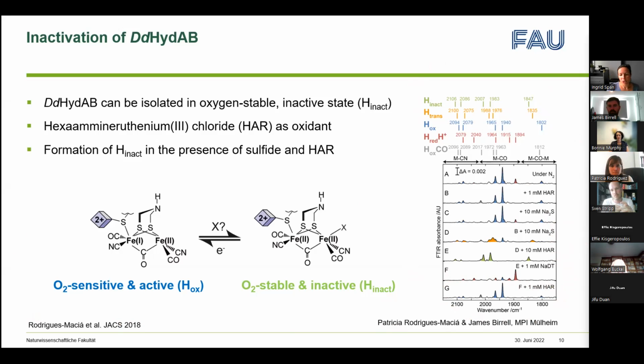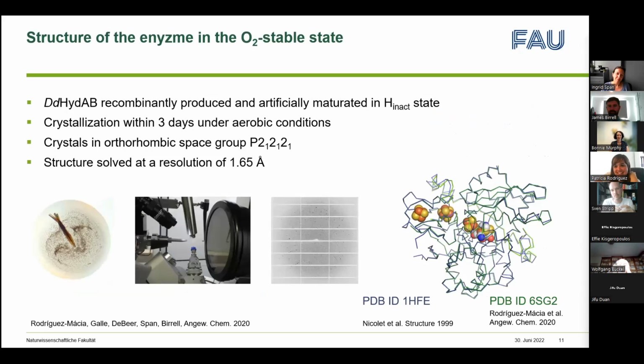And this all started, as usual, with a beer in front of a poster at a conference and me asking why they had not crystallized it yet. So the next step was that they sent enzyme and we crystallized it. Just a bit of background: the enzyme was produced recombinantly, maturated artificially and then transformed into the H-inactive state. We crystallized the enzyme within 3 days under aerobic conditions, because it is oxygen stable for approximately 3 days. This is what we know.